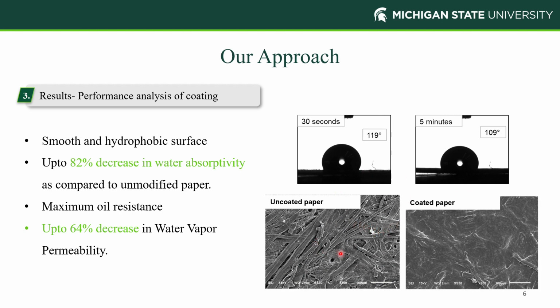As you can see in this SEM image here, the uncoated paper has a lot of pores on the surface and a lot of ridges, which are completely covered in the case of coated papers. And the smooth coated paper here gives a very good water contact angle of above 110 degrees, which proves that it's completely hydrophobic.